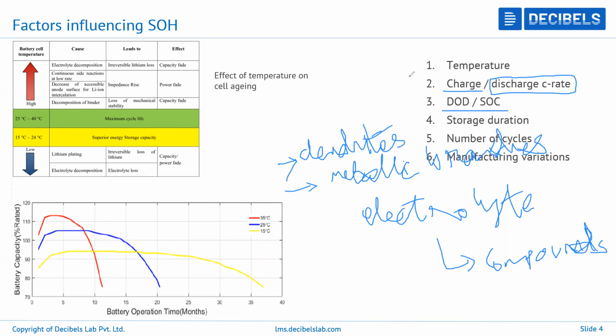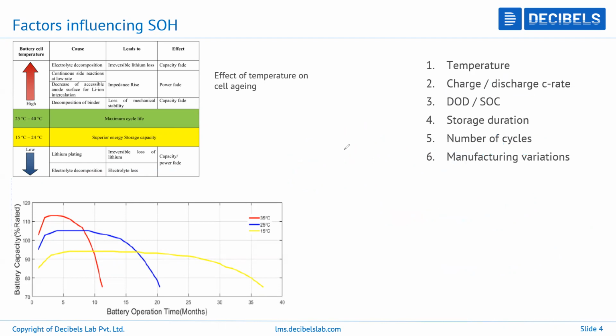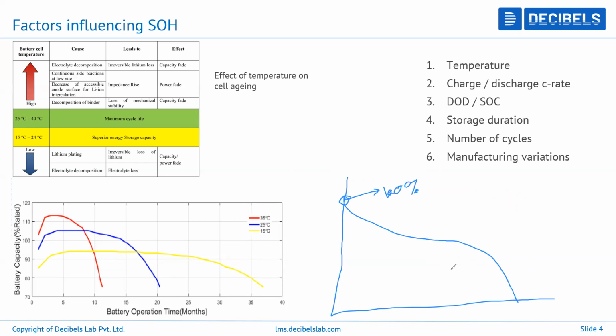Then we have even the depth of discharge. So say, for example, this is the operating voltage of a cell, right? If we are starting at 100%, this is the 100% state of charge, and this is 0%. The cells will usually last longer if you have the cutoff voltage over here itself. So if suppose this is 2.7 volts, then this will usually be taken care of by the BMS itself. So this will be somewhere around 3 or 3.1 volts. This is again user dependent, so they can set it as per their requirements. So cycling the cell between these values will cause the cell to last longer, right?